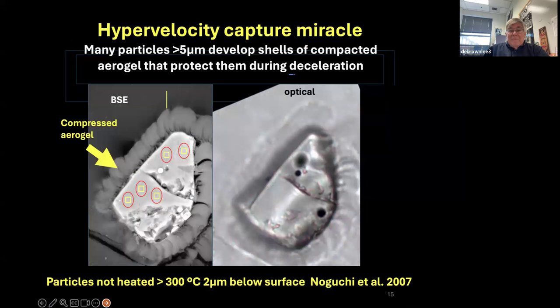Hypervelocity capture is a miracle, really. It's going into silica aerogel, made out of sort of 30 angstrom size solid silica particles in something only a few times denser than air, a superlative material. But there's a miracle that goes on in at least some fraction of particles larger than a few microns: they develop a cocoon around them of compressed aerogel.